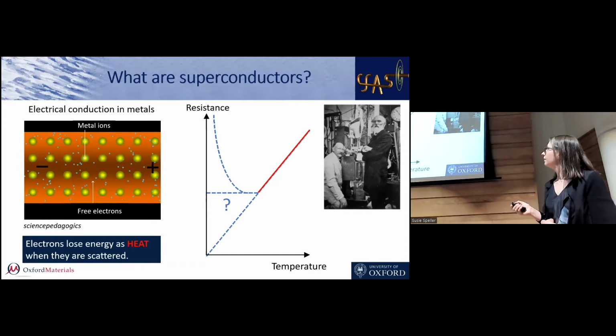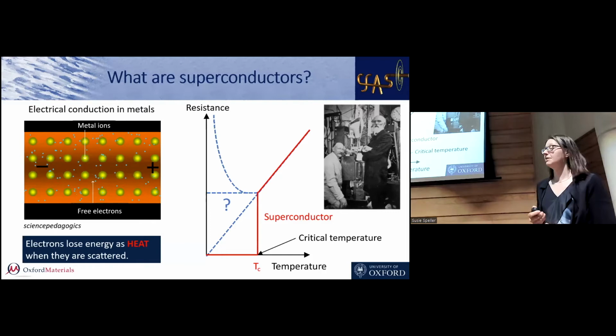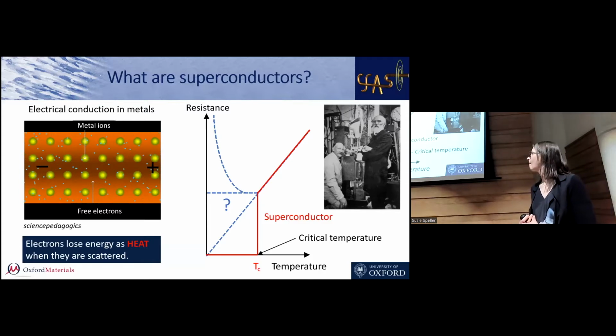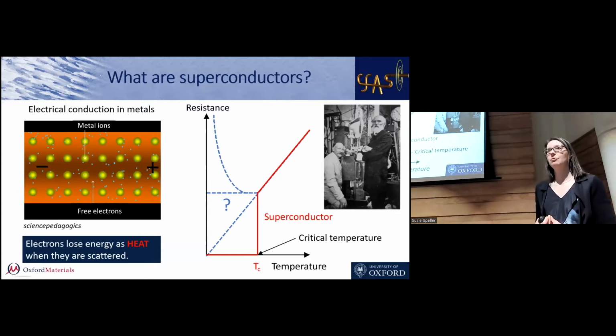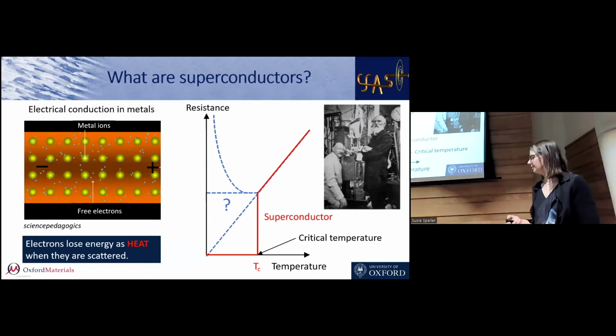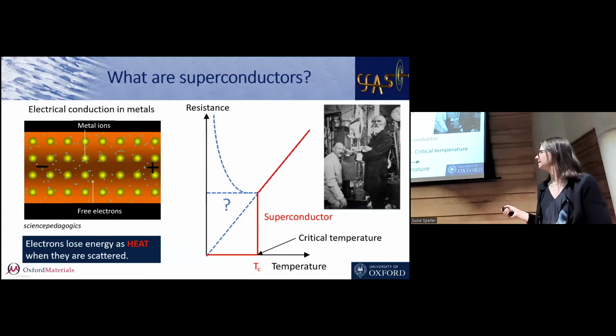So what did he find when he cooled down mercury to these very low temperatures? Well, it surprised him because he found that the resistance of the mercury suddenly dropped from this value here to absolutely nothing when he got to very near his lowest point, 4 Kelvin. And what's more, if he heated it up a bit, the resistance would come back again, and he could do this repeatedly. And this really is zero resistance. To all intents and purposes, it's absolutely nothing, this resistance here.